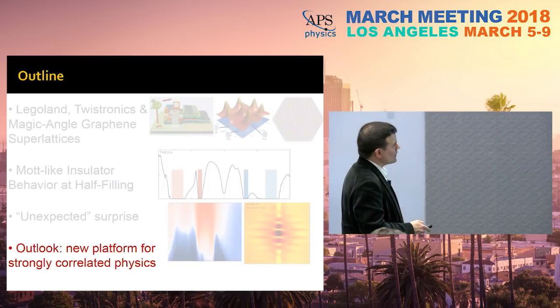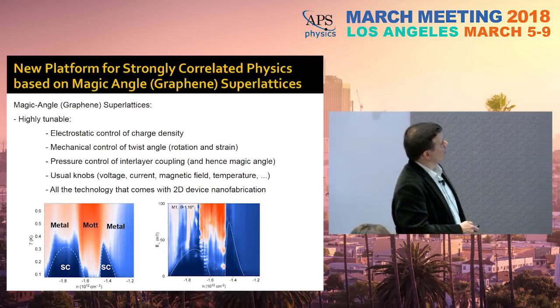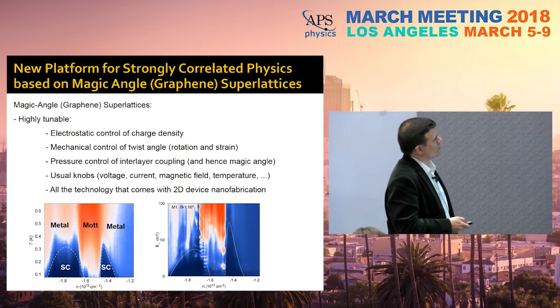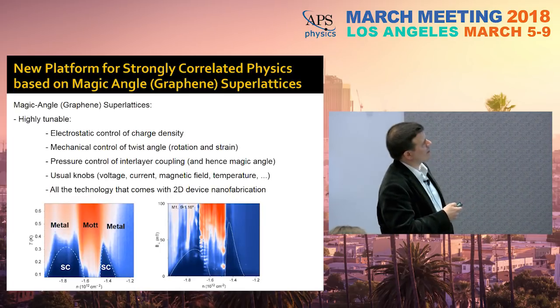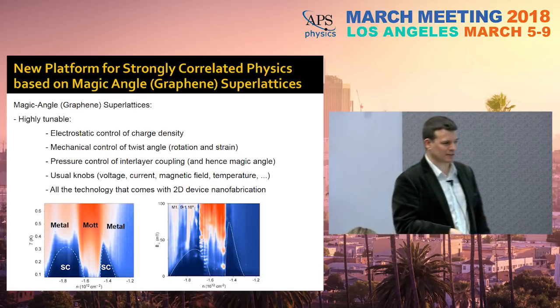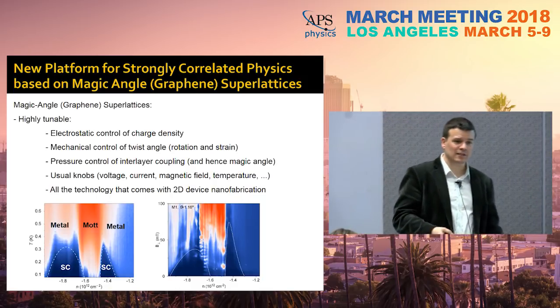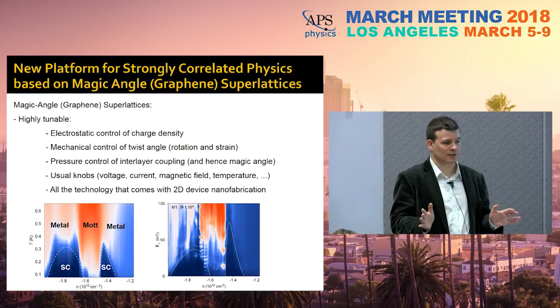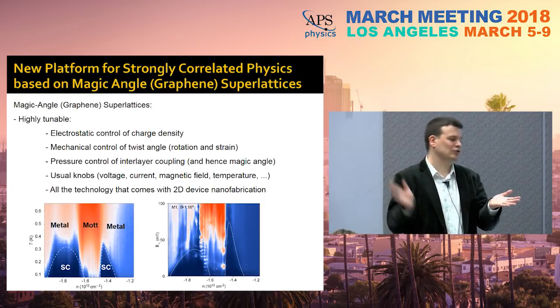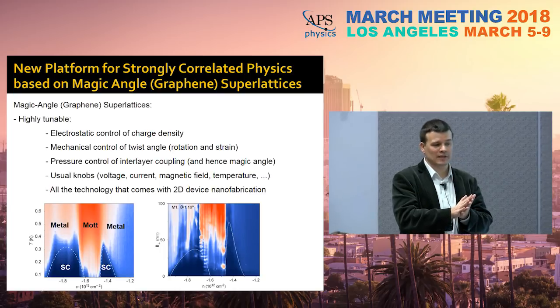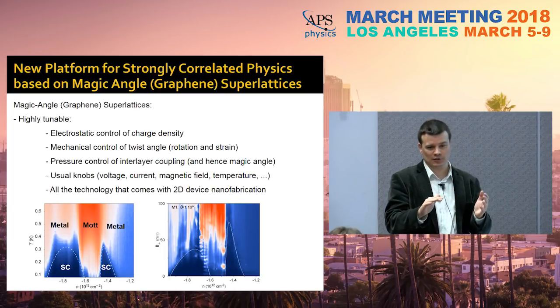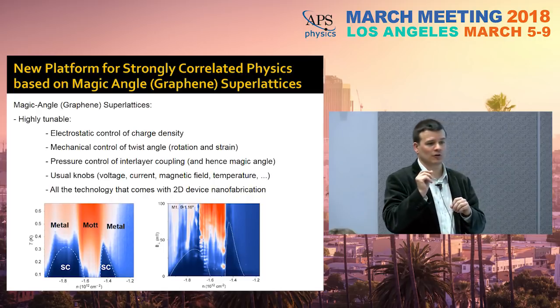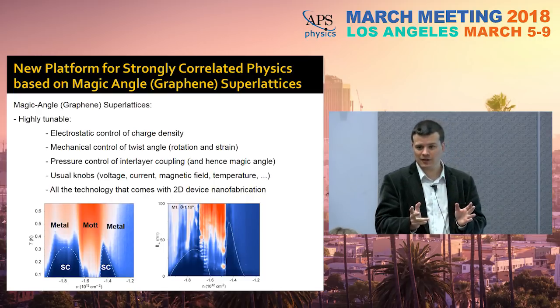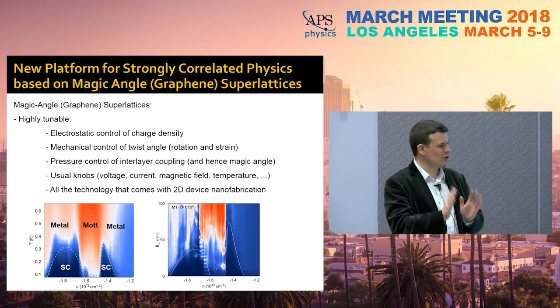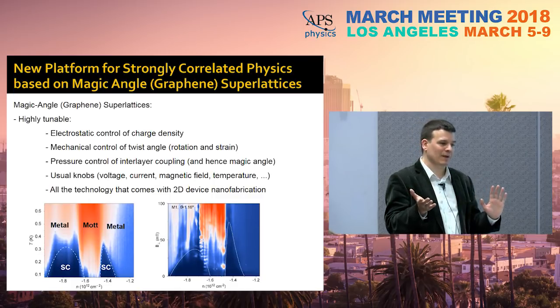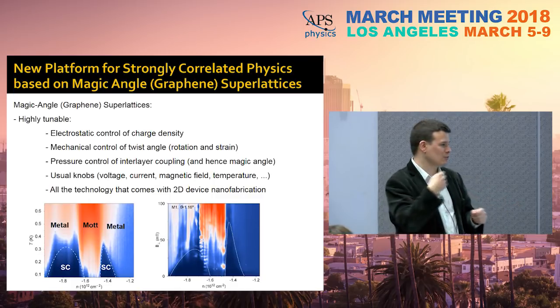So now, let me just say a couple of words. This is a new platform for correlated physics, which is based on magic angle, and I put here in brackets graphene superlattices, because it actually turns out that this is totally generalizable to any 2D material. You put any 2D material on top of another 2D material, and there's always a magic angle for which flat bands will occur. This can be for semi-metals, for semiconductors, for metals, okay? The details vary substantially, but there's always a magic angle, which will develop flat bands where strong correlations will appear, each one with its own flavor.